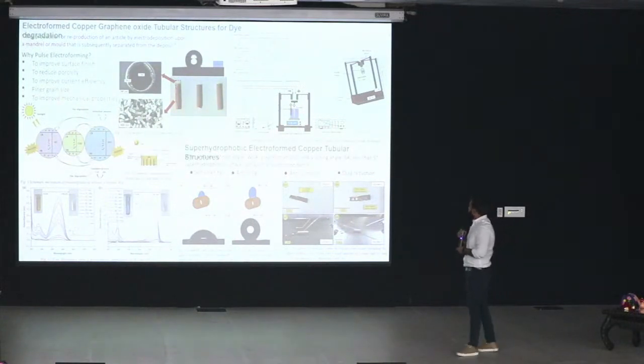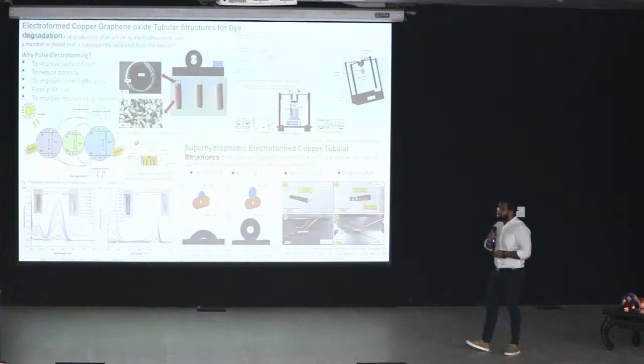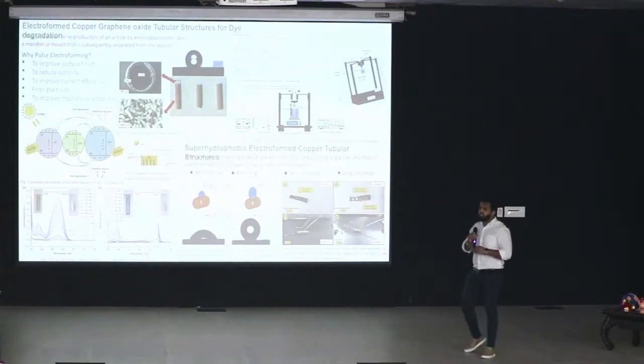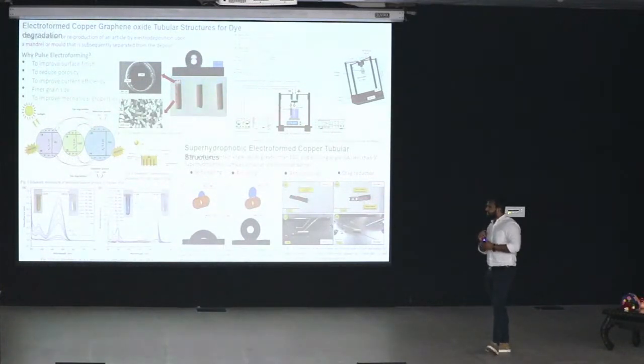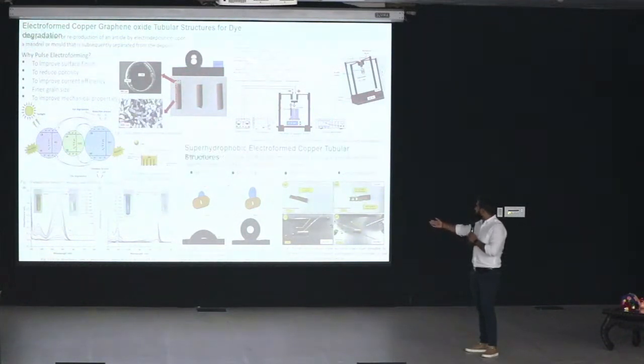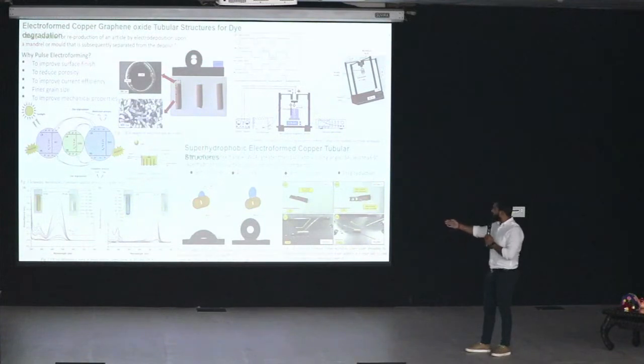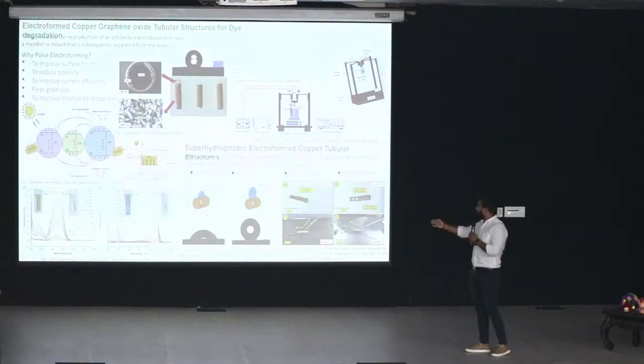Another application of this superhydrophobic electroformed microtube is in the field of fluidic transportation devices, miniaturized devices like microfluidic devices or biomedical devices, or in the field of micro heat exchangers. So our aim is to convert this as-received hydrophilic microtube into a superhydrophobic microtube so that it could not absorb water droplets or any liquid when we flow it inside the tube. So from figure 6, you can see that the water contact angle has changed from 57 to 156 degrees, from hydrophilic to superhydrophobic, when we converted the as-received copper microtube.